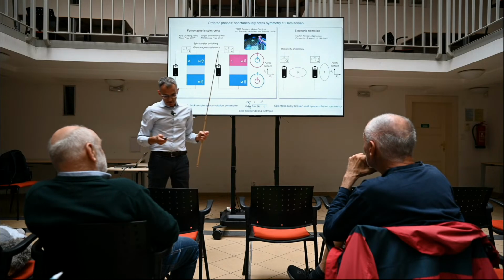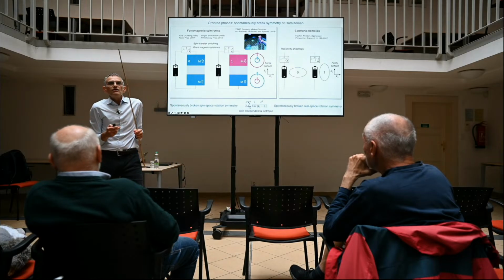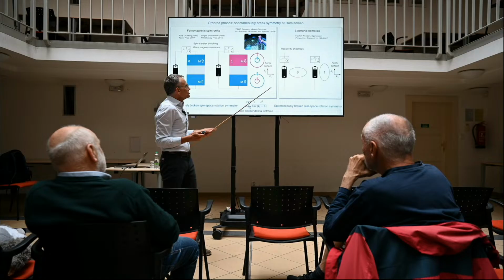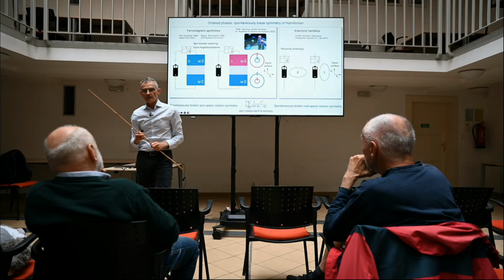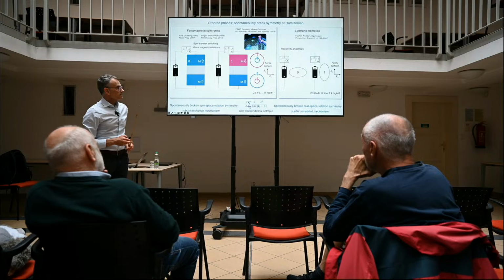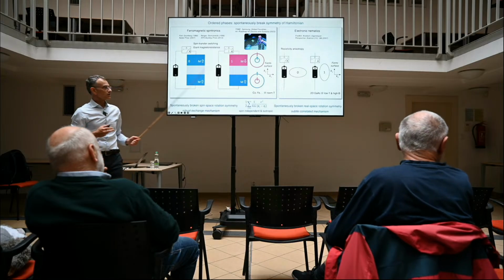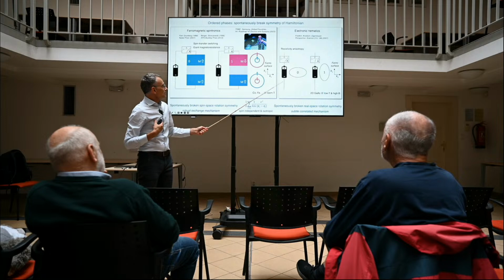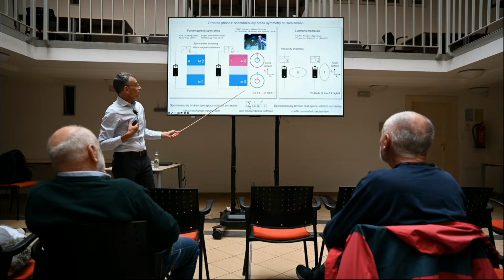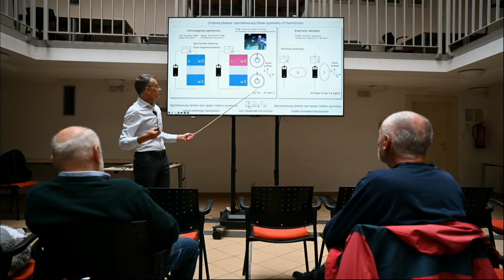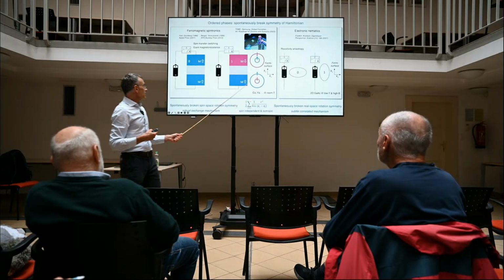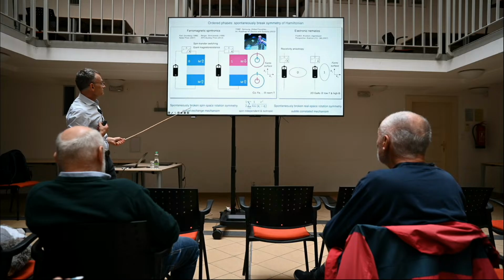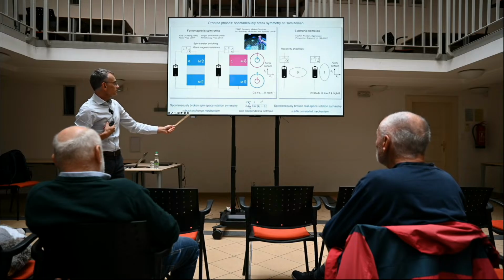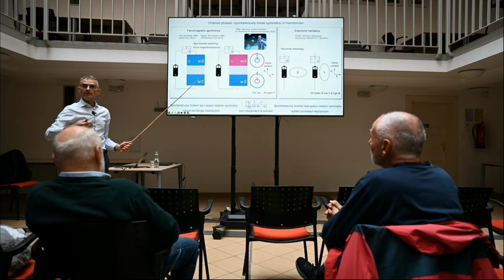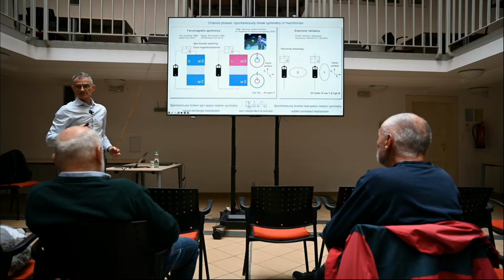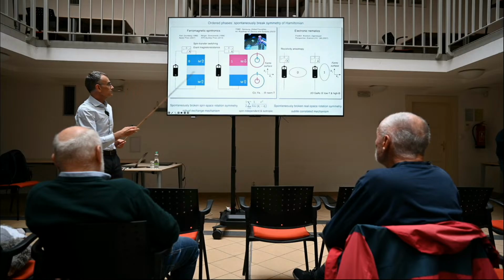Now, first of all, it's not very easy to imagine what kind of external knob I can use to actually choose which of the states will form in the ordered phase. But it's sort of the least of the problems when talking about this phase. Because ferromagnetism, we know, can occur in systems like cobalt, iron, transition metals. They are actually ordering at room temperature, and we know very well that the ordering mechanism is very robust. It's this electron-electron interaction combined with the Pauli exclusion principle, and this is what we call exchange mechanism. And this can be very robust. It can work easily at room temperature.